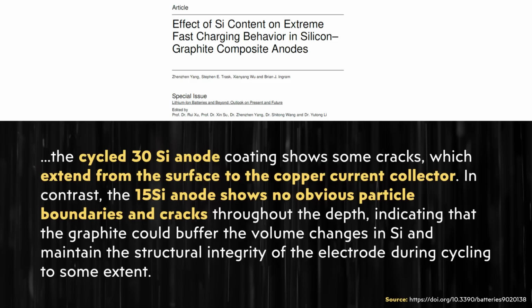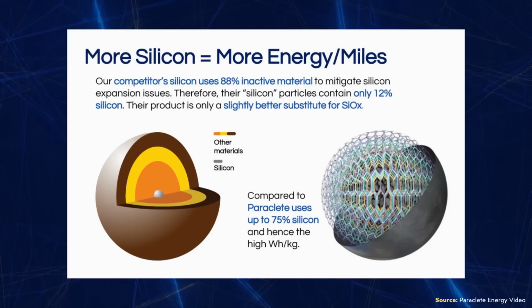So obviously that's a bad thing, but with the 15% silicon anode, it's written here, quote, "the 15Si anode shows no obvious particle boundaries and cracks throughout the depth, indicating that the graphite could buffer the volume changes in silicon and maintain the structural integrity of the electrode during cycling to some extent." So obviously this is just one test, but I gather from this that having around 15% by weight of this silicon product in a battery may be kind of the sweet spot. It will increase the energy density of that battery cell quite a bit, but maybe still mitigate any of that damage that's caused by that swelling, because, once again, that 15% silicon anode battery seemed to not have the same cracking as the 30%. So it looks like this Paraclete Energy product does work well, at least in this particular test, at mitigating the damage of silicon swelling.